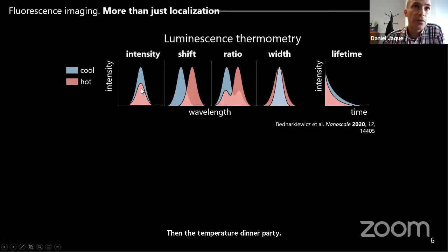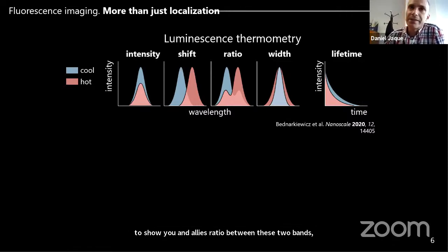So for example, here you have different examples of how you can measure temperature depending on your nanoparticle. Some nanoparticles emit light. The intensity of the emitted light depends on temperature. So if you register the emitted light, you can get information about the temperature of the nanoparticle. Some other nanoparticles, like the quantum dots, shift the emission spectra when you change the temperature. In this case, you can get information about the temperature by measuring where is the center wavelength of this band. Some particles show 2 bands, and then the ratio between these 2 bands changes with temperature. So you analyze the ratio between these 2 bands, and you can get the information about the temperature of the nanoparticle. If your nanoparticle is in the brain, for example, you can get information about the brain temperature. If your nanoparticle is in the liver, you can get information about the liver temperature.